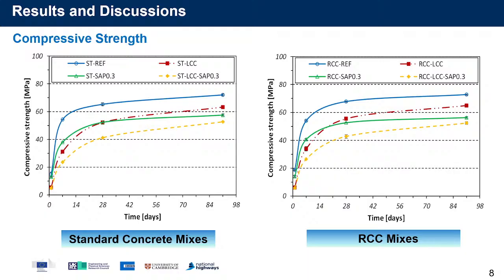This slide shows the results in terms of compressive strength development over time. As you can see, the best performance was achieved in both groups of mixes by the reference concrete, in which 100% Portland cement has been used. By replacing a proportion of that with GGBS, we have seen a strength reduction in all concrete mixes. When I used superabsorbent polymers, since I used additional water to compensate for the consistency of the concrete, you can see that there is also a reduction in compressive strength. And the worst performance was achieved when we have the combined use of SAPs and GGBS in concrete.